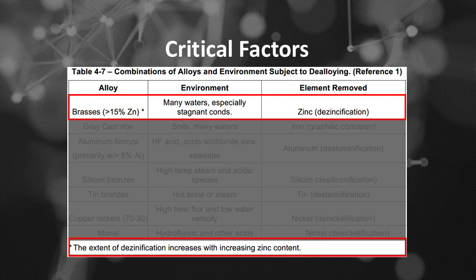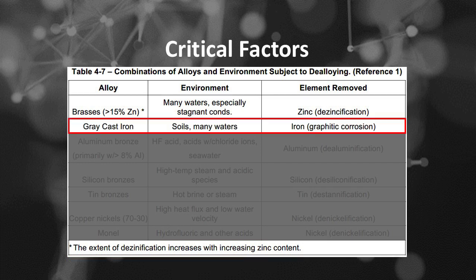Table 4.7. Combinations of alloys and environment subject to dealloying. If alloy is brasses, greater than 15% Zn, the extent of dezincification increases with increasing zinc content, and if environment is many waters, especially stagnant ones, then element removed is zinc, or dezincification. If alloy is gray cast iron, and if environment is soils, many waters, then element removed is iron, or graphitic